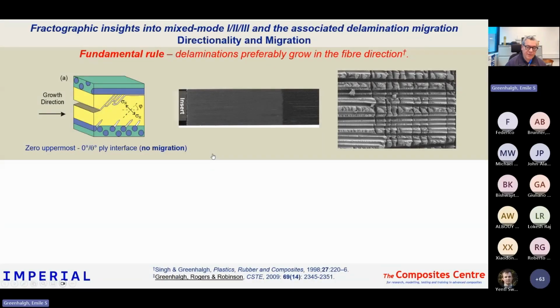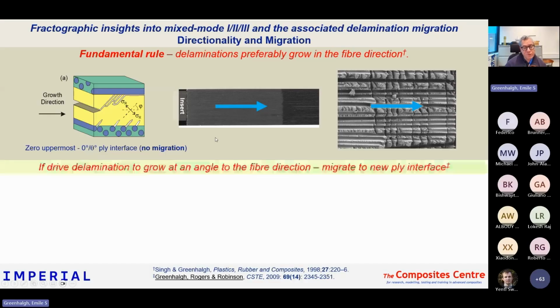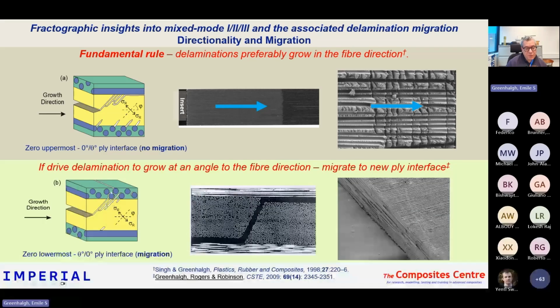But when we look at multi-directional laminates, we start to see another process occurring. What comes out of this is a fundamental rule that delaminations want to grow along the fibers. This is really a fundamental aspect of how delaminations grow in composites. And if you design your interface such that the upper ply, under the loading conditions like I showed earlier, is in the growth direction, so this is a UD for instance, then the crack will just grow along that interface. This is a fracture surface of a mixed mode delamination specimen, and there's no migration processes. But if we try and force a crack to grow in a different direction to the fibers, then what will happen is we get migration occurring. The crack, initially starting at an interface, will migrate through the off-axis ply into a new interface.